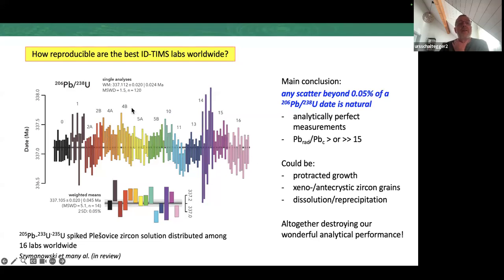analyses from these labs align along a 206-238 date, which is highly precise at the value which is certified. And actually the scatter of this whole population is within analytical scatter. It's just still acceptable at an MSWD value of 1.5. However, when we plot the weighted means of each lab, it's clear that we have excess scatter. But nevertheless, even if we take this excess scatter into account, we get to a standard deviation of 0.05% of the 206-238 uranium date. So that means, in other words, that any scatter from ID-TIMS dates, a set of scattering dates, which is beyond this 0.05% of the 206-238 date is natural.